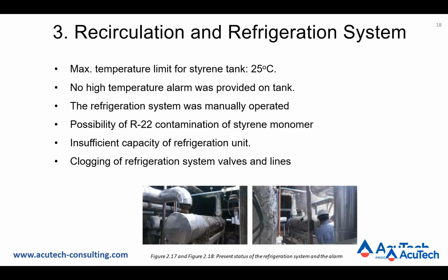There was a practice to operate the refrigerant system manually during 8 a.m. to 5 p.m. every day. However, on 6th May, the system was stopped at around 3:45 p.m., assuming that the tank is cold enough.